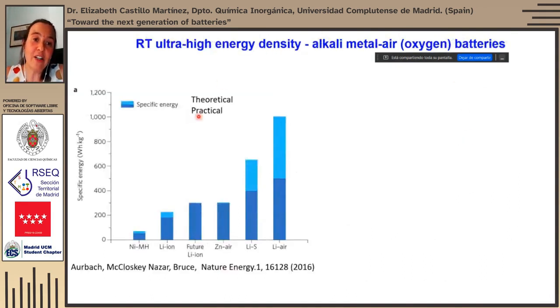If we were to compare the theoretical and practical specific energy in watt-hours per kilogram of different battery chemistries, we see that the lithium-air is by far the one that shows the largest capacity. But also, if we account for the contribution from all the external components like casing and current collectors, the practical capacity is not that much. Nonetheless, the theoretical capacity approaches that of gasoline, and that's why lithium-air batteries are in the spotlight for making it into electric vehicles.